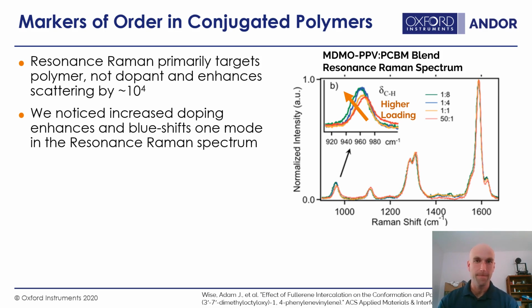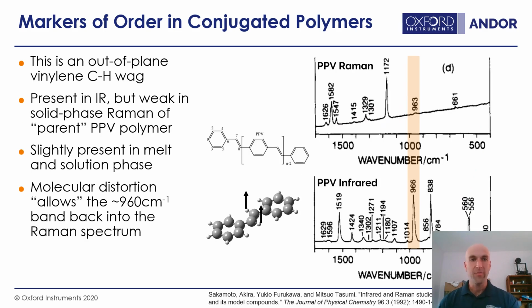So it turns out this is an out-of-plane vinylene CH wag, and I've shown in this cartoon here the displacement vectors. I couldn't get this to animate, but if you can imagine my hand is the plane of the molecule, this is a mode that goes in and out of the plane. So this is a symmetric mode, but it's out of the plane of the molecule. It is present in the infrared pretty strongly, as you can see. These are Raman and IR spectra of the parent polymer without the side chains, polyphenylene vinylene, shown here schematically. It's not present in the Raman spectrum, resonant or non-resonant, and it is quite strong in the infrared spectrum. So it is an infrared allowed vibration.